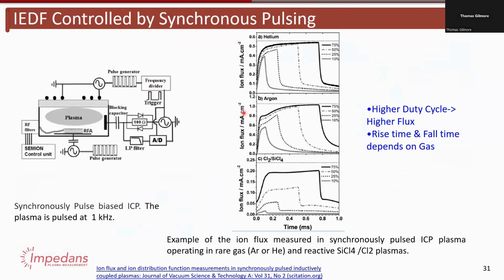One thing to note is that pulsed RF is quite complicated because the plasma has to strike and it also decays, and how it does that is very gas dependent. If you're using argon, it's straightforward, but if you're using molecules, the molecules go through different chemical states. A molecule has rotational states, vibrational states, dissociation states, and as the power comes on and energy is being delivered, it has to go through all these different modes. So you can have a really chemically dynamic plasma when you're pulsing. In fact, certain reactions take a minimum amount of time. So by changing the pulsing frequency, you can control what species form and what don't.